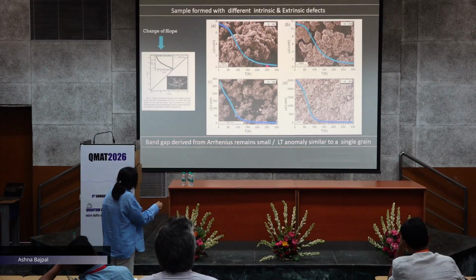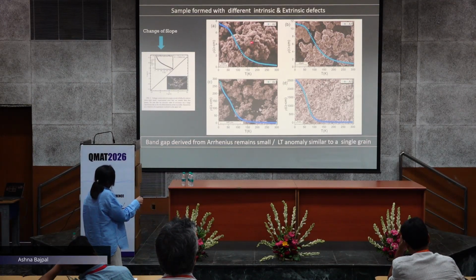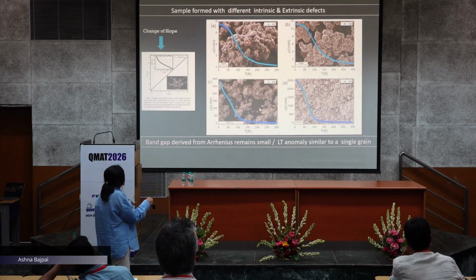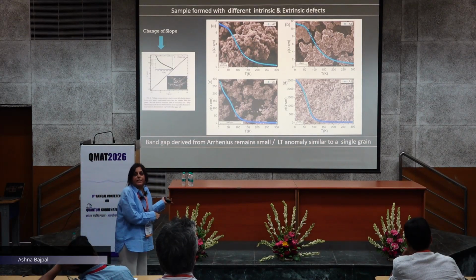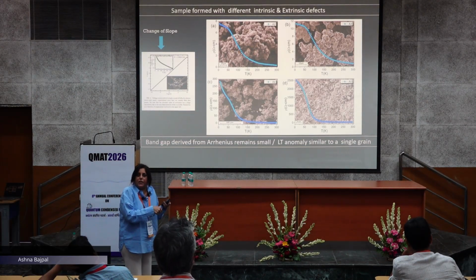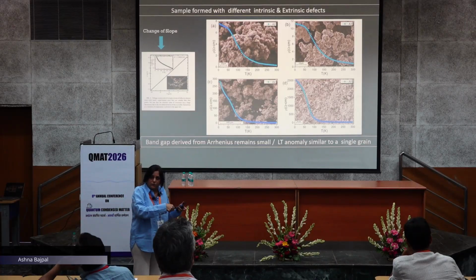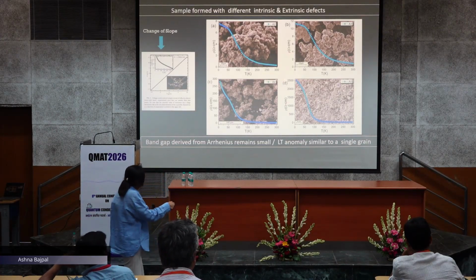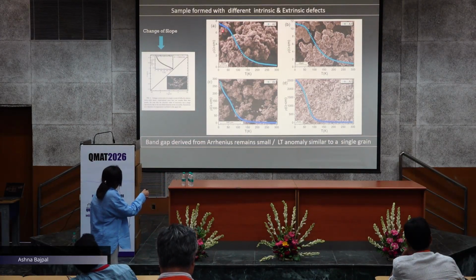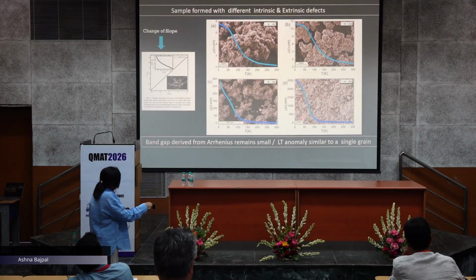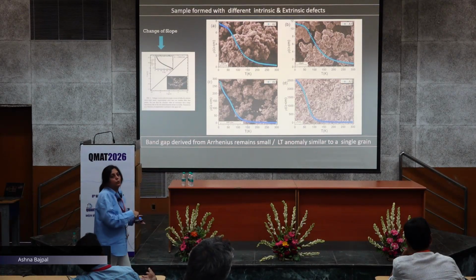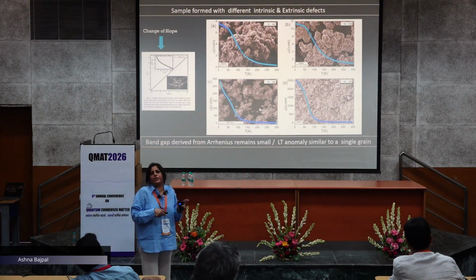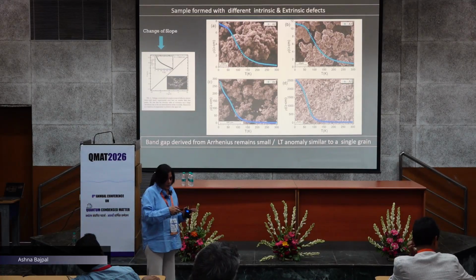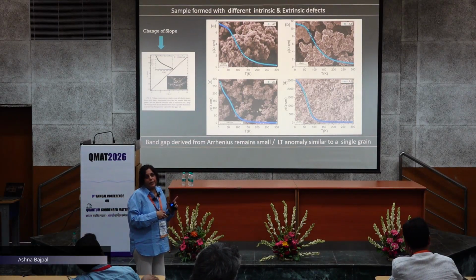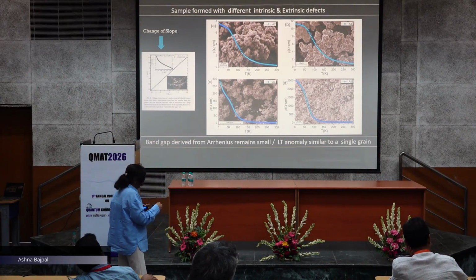Nevertheless, only in this region Arrhenius fits. Even by variation of grain size, extrinsic and intrinsic defects, basically you can push in defects and make your conductivity very low, resistance very high, even by a few orders of magnitude, and the band gap still remains low. It is between 50 to 100 millielectron volts. So this was one question we were trying to address.